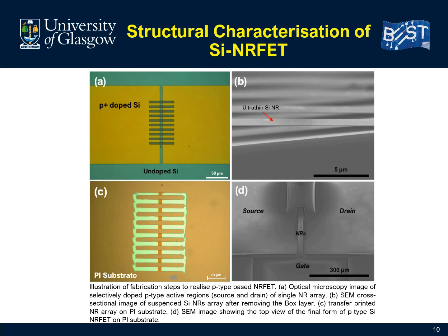Figure A shows an optical image of the p-type doping profiles of the active regions, source and drain on the source wafer. Since achieving a doping is a challenge once the structures are transferred on flexible substrate because of the thermal budget issue, without heavy doping in source and drain, it's not possible to achieve an ohmic contact, and therefore realizing a transistor. So figure B demonstrates the SEM image of the anchored nanoribbons